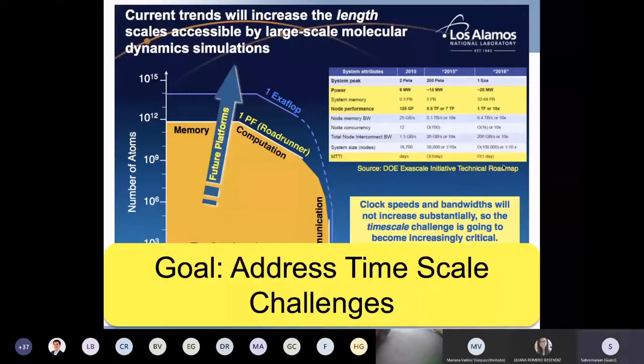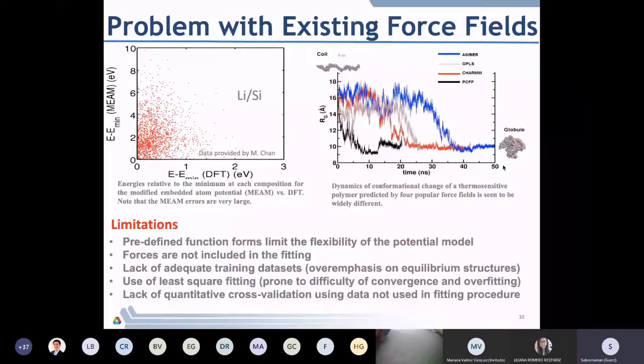So what are the problems with existing force fields? We want to highlight a couple of examples. This is a lithium silicon system which has mixed ionic covalent characteristics. If you compare the cohesive energies for various different configurations that are highlighted by these red dots, these are values obtained from DFT, and these are values obtained with a modified embedded atom method, which is a very powerful MD model that typically works for most systems.